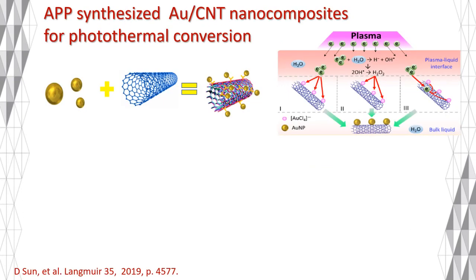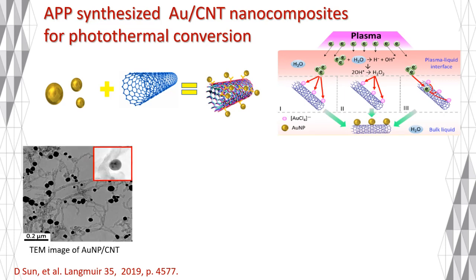Both carbon nanotubes and gold nanoparticles have gathered significant interest in the biomedical field, such as cancer therapies, drug delivery, and bioimaging. With this in mind, my objective was to create a hybrid material that combines both carbon nanotubes and gold nanoparticles using this APP plasma technology. And the aim was to harness the synergistic effect of these two materials. Through the APP technique, we successfully synthesized the gold CNT hybrid material, where the gold nanoparticles were attached to the surface of the carbon nanotubes via its surface functional groups.